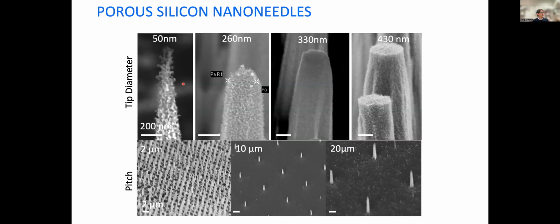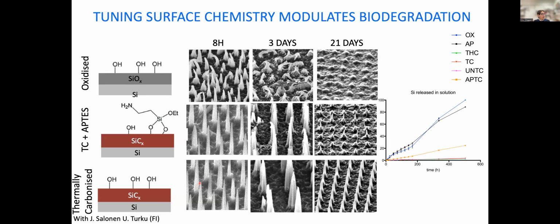So the material in particular that we use is based on porous silicon. As you can see here, it is porous to 40 to 50%, and we can very precisely control through microfabrication the size of the tip, the height, and the density of these structures, so that we can regulate the interaction with the cell. Very importantly, and differently from many other types of nanoneedles that can be generated from other semiconductors or metals, because we use porous silicon, we can also tailor their degradation.